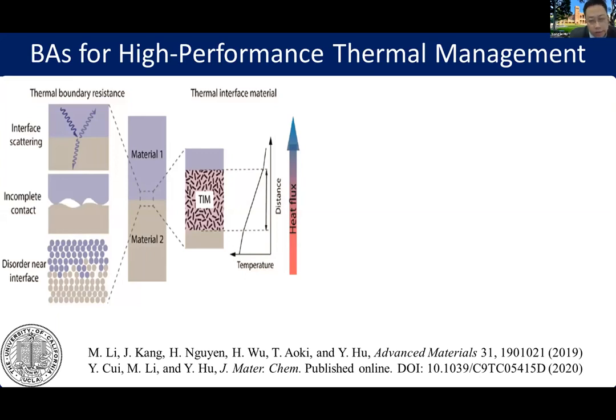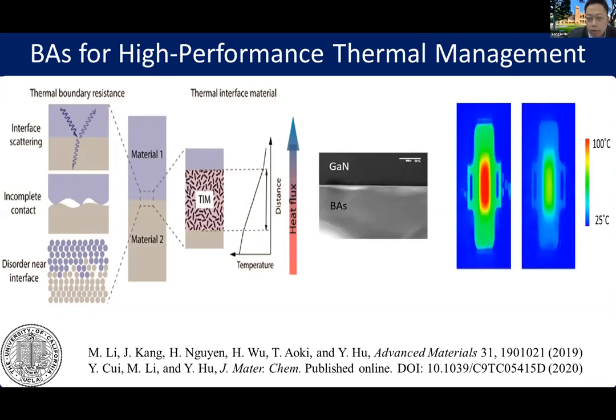So the important next step is experimental integration and measuring the thermal management performance. Indeed, my group recently successfully integrated gallium nitride and boron arsenide, and we found the near junction thermal resistance is significantly improved over that with diamond. And when you further integrate boron arsenide with a high power device during its operation, you can clearly see that the hotspot temperature was significantly reduced. So this is a very exciting result. It verified that, from theoretical prediction to experimental demonstration, boron arsenide can be used as a high performance building block to achieve high performance thermal management of power electronics.